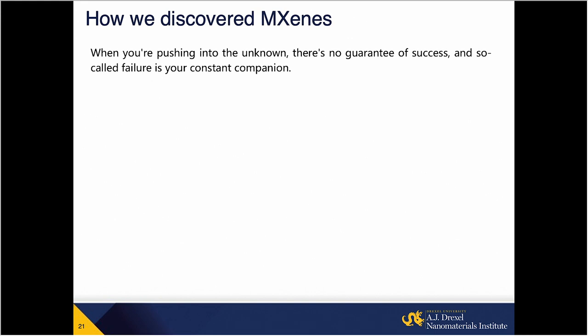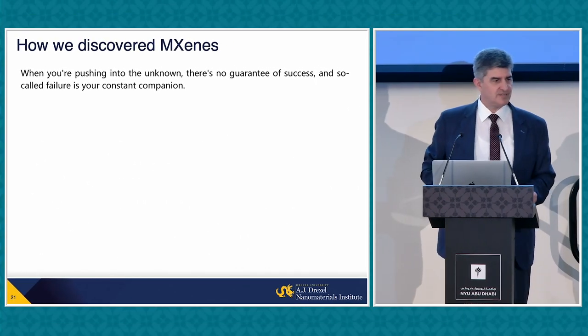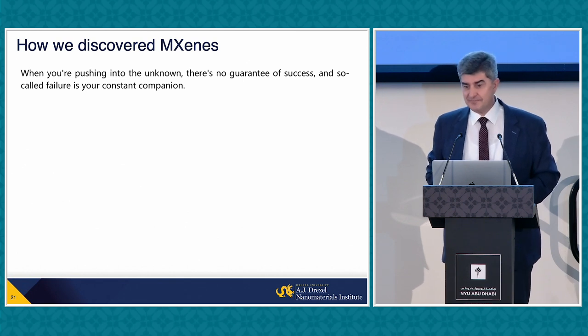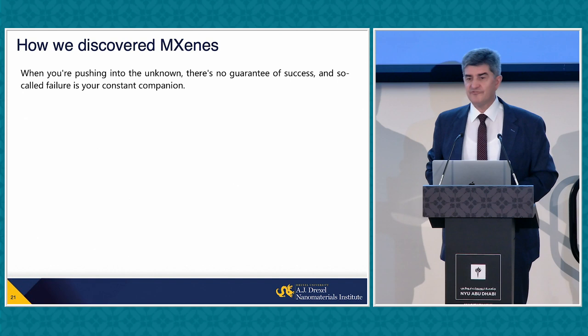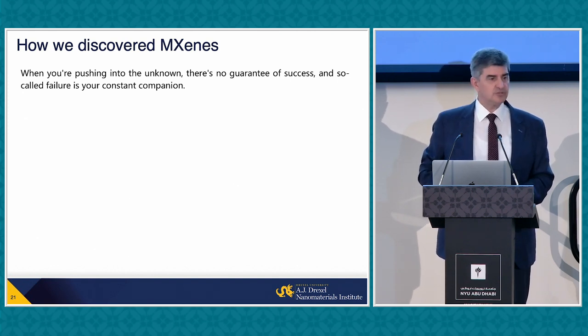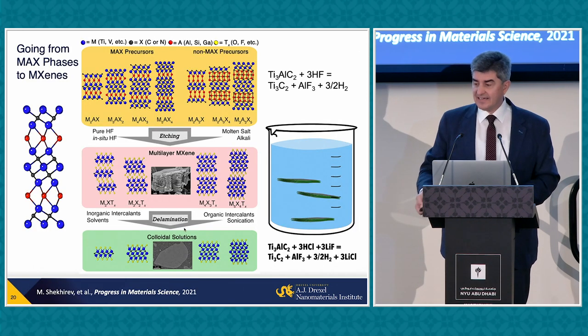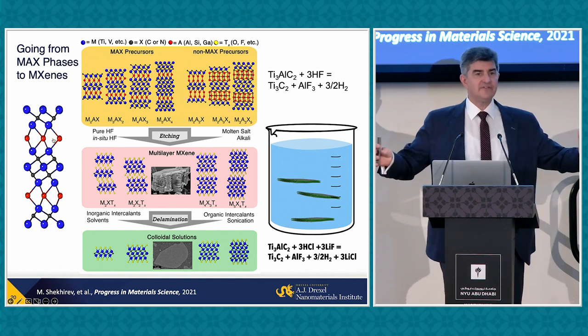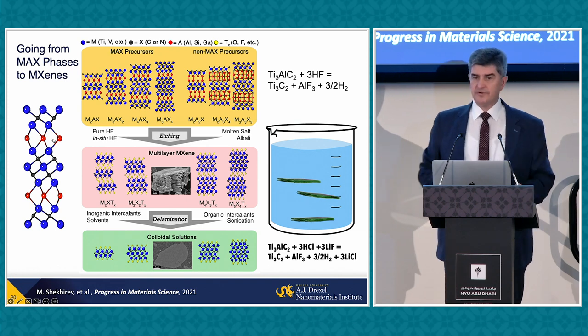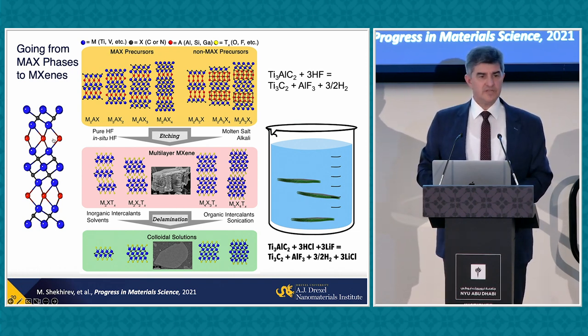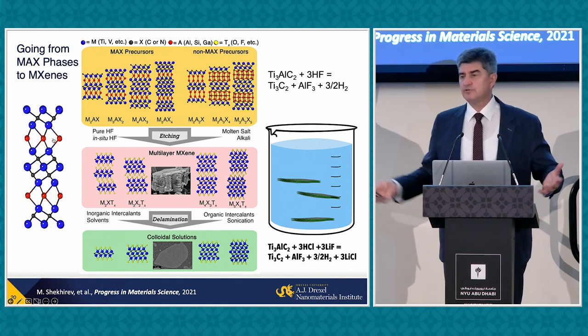Now, why did we do it? Not because we were initially that smart and I wanted to show my colleague that he's wrong and I'm right. We did it because I had another idea which actually failed. I thought that for battery electrodes, we can take these MAX phases, oops, sorry, I wanted to go back for a second, containing silicon with these layers of silicon, conducting layer of carbide with carbon, silicon that can take more lithium than carbon, and it's layered like graphite, and I thought it would be a great anode material. I asked one of my PhD students to do DFT calculations, and he calculated the barrier for getting lithium in is not very high, it should be possible.